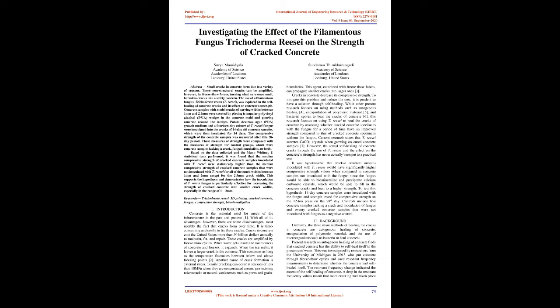7. Analysis of results. The original hypothesis was that cracked concrete samples with T. reesei would have higher median compressive strength values when compared to their cracked counterparts not inoculated with T. reesei. The hypothesis appears mostly correct from an analysis of the data. For example, a visual analysis of Table 1 reveals that for each of the different crack widths, cracked concrete samples inoculated with the fungus had higher mean compressive strengths when compared to their counterparts without fungus.